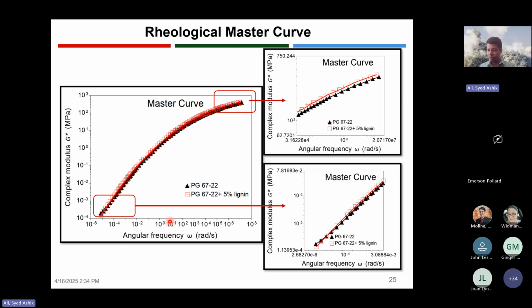through some superposition principle and stuff. And so what we have found is that if we use the complex modulus G star value at different angular frequency for PG67-22 and PG67-22 with 5% lignin, they're almost the same. There is not much difference between these two at the higher frequency and also at the lower frequency as well.